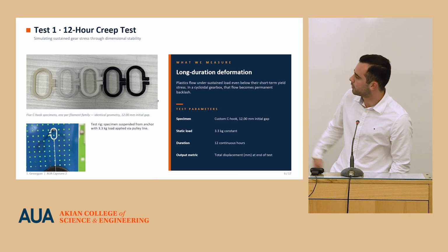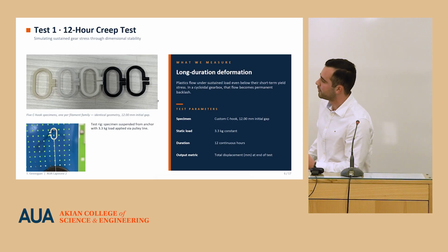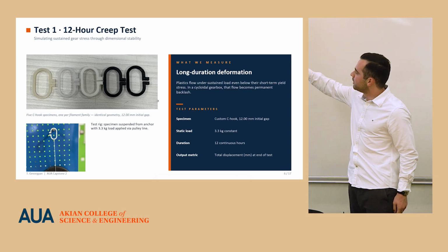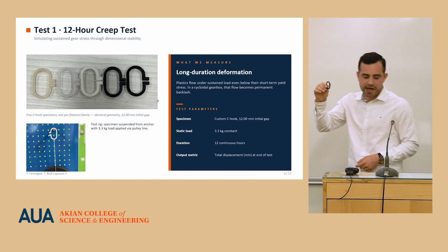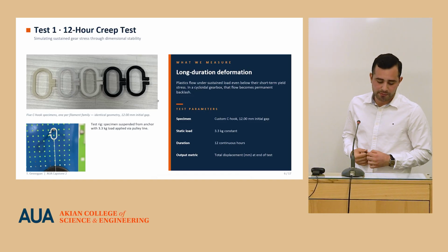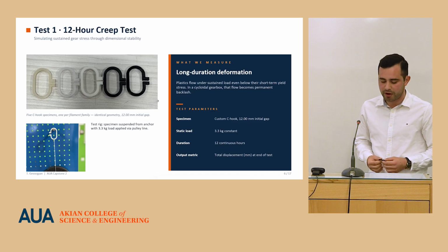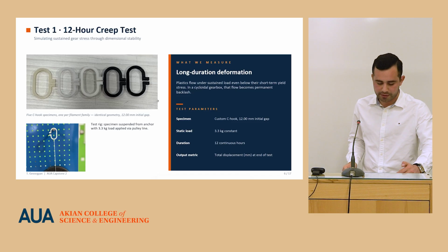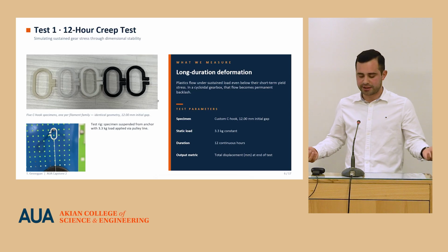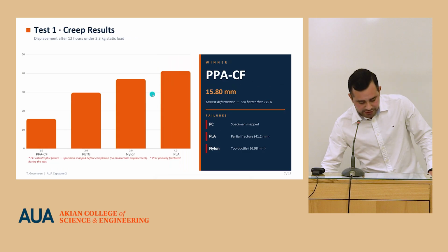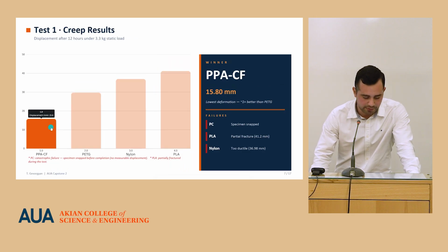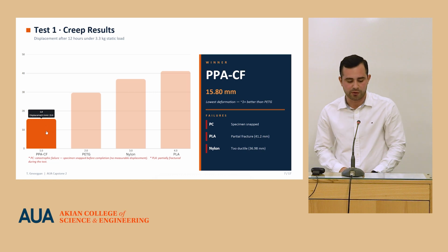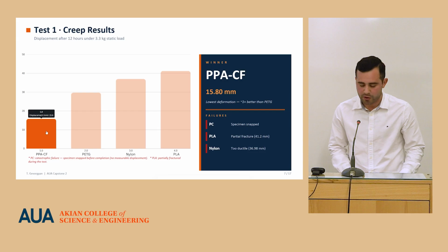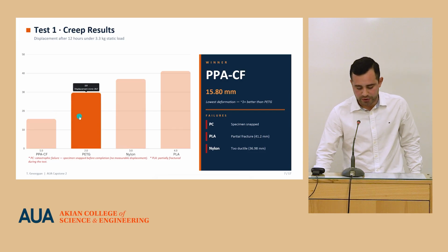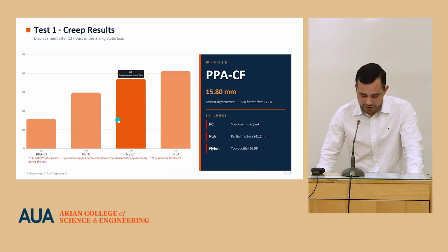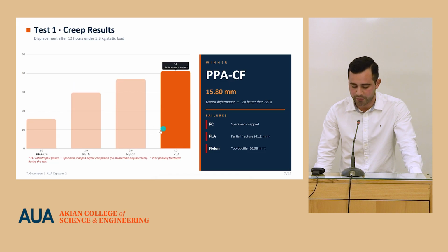As you can see, I created and printed these C-shaped components. Each one has this gap between these two lines inside. And in the setup, I hung a 3.3 kilogram load from it, and after 12 hours I measured the distance in this gap to understand how much it deflects. So here you can see the results from these tests. Carbon fiber was the winner because it deflected only from 12 millimeters to 15.8 millimeters, only 3.8 millimeters deflection. PETG was second with 29.7 millimeter deflection, nylon third with 37 millimeters, and PLA last with 41.2 millimeters.